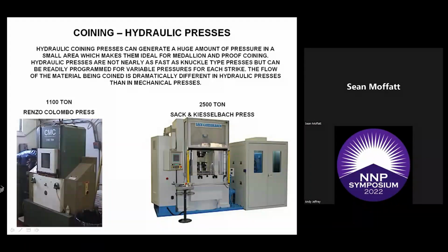The flow of the material being coined is dramatically different in hydraulic presses than in mechanical presses. In your mechanical or your knuckle joint presses, the press is mechanical. The die is going to push to the same spot every time. Nothing's going to change. For a hydraulic press, you can sit there and program how hard you are going to hit the coin each time. So if you're making a nice proof high relief medallion or something like that, you can start with the first hit at 150 tons, the second one 200 tons, and the last one 400 tons. What that does is it reduces the metal flow, which reduces the wear and tear and the striations on your dies and on the finished coin.